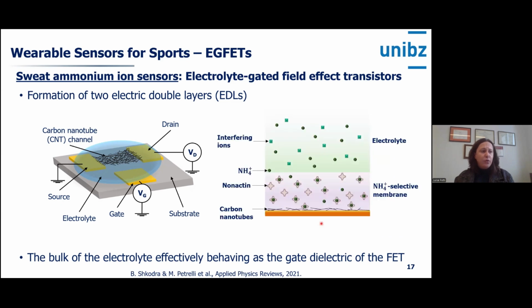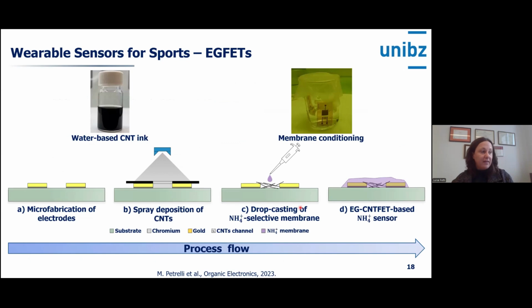Now, if you use an ion selective membrane, you allow only the passage of the ions of interest, in this case the ammonium ion, through the membrane, and only those can interact with the semiconductor, and thereby change the conductivity and produce a variation in the current that can be detected. And that leads to the sensor characteristic, basically. This is quickly how the devices are made.